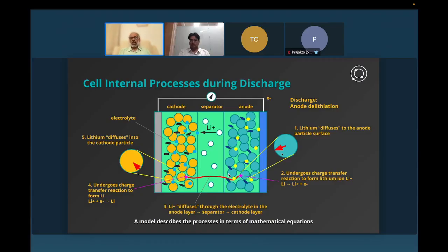So starting from the right, number one is lithium diffuses to the anode particle surface. So the lithium is sitting right through the anode particle, and once the discharge process starts, the lithium from the interior of the anode particle starts migrating to the surface. And this process is called diffusion through the solid, or solid state diffusion. And once it reaches the surface of the anode particle, it sees the electrolyte, and that's number two.